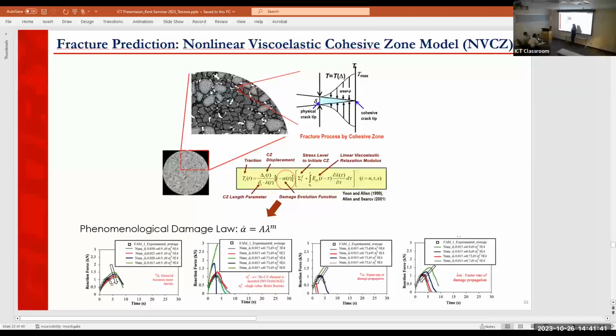The higher the sigma F, this term here, which is the stress initiation criterion, the longer it's going to take to create a damage zone. This was very commonly observed in more brittle materials, and the lower sigma F is observed in materials that are less brittle. The higher the A, you can see from this relation, the higher the damage propagation rate. So you can relate it with that. Same thing, the lower the M, the faster the rate of propagation.